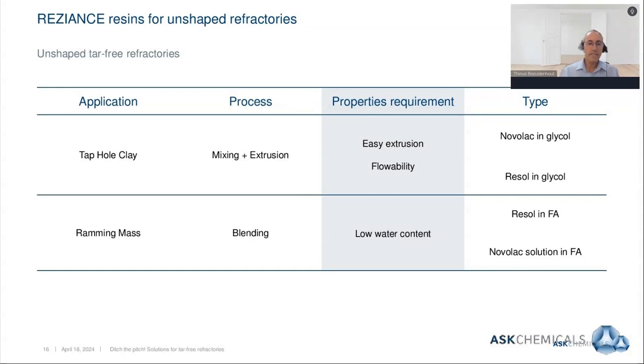In the case of ramming mixes or ramming masses, which is done by dry blending, always consider the water content in this mix for the sake of the final quality and to ensure that you do not get cracking in the furnace lining. Here you would consider phenolic resins of the types resols or novolacs in furfuryl alcohol as a reactive solvent. Next slide, please.